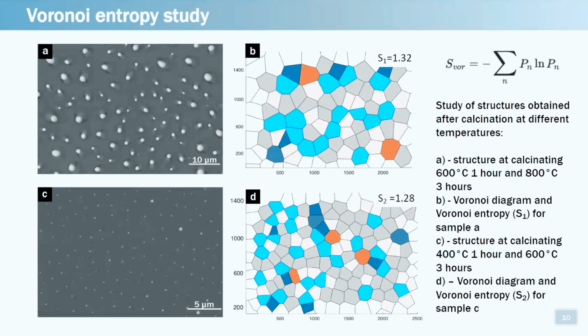We used the combination of two software packages, MATLAB and ImageJ. In figure A, we can see the sample that was obtained at 600 to 800 degrees. And in figure C, we can see the sample that was obtained at 400 to 600 degrees. The value of Voronoi entropy for the samples that were obtained at different temperatures represents the structure with conserved periodicity, that was proven by the calculation of Voronoi entropy.